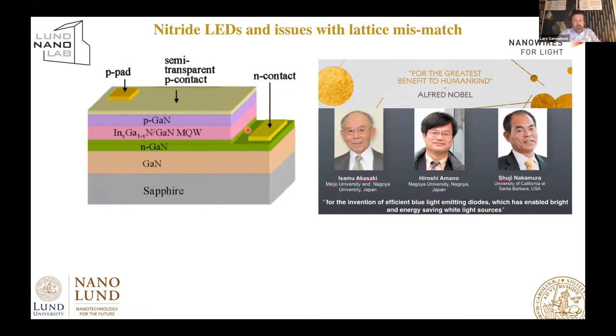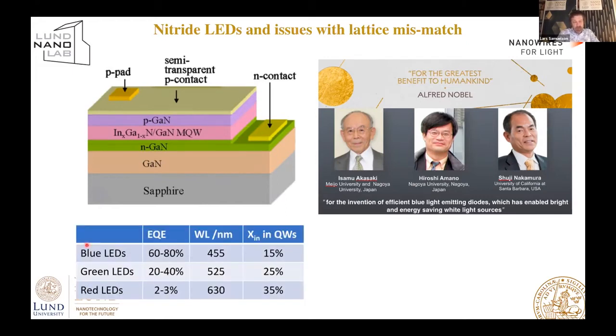There is a problem if you're trying to use this technology for longer wavelengths. That's illustrated down here. If you make a blue LED, things are fine. You have not so big a lattice mismatch between the indium gallium nitride in the quantum wells, which is 15% indium, and that in the gallium nitride substrate, which is 0%. Things get a little bit more problematic for the green. There you have 25% indium, corresponding to quite severe lattice mismatch. And now you're down from the very high 70, 80% efficiency for the blue to say 30, 40 or so in the green. And of course, if you go all the way to the red, you have huge differences.